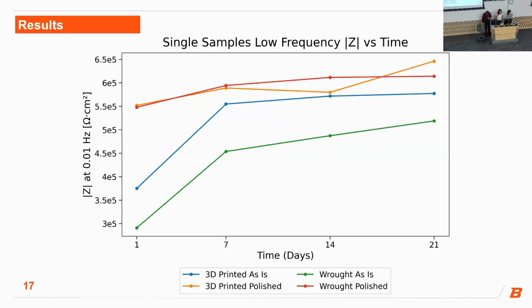But looking at this plot, the impedance increased with time for all 4 of our single samples. And like Brylee mentioned, this indicates the formation of a passive oxide film, which improves corrosion resistance. There are some moments of what we think is repassivation, where the surface breaks down and repairs itself. We can see that in the 3D printed polished sample, which is indicated by the orange line. As you can see, the impedance values start to dip down and then increase up again.